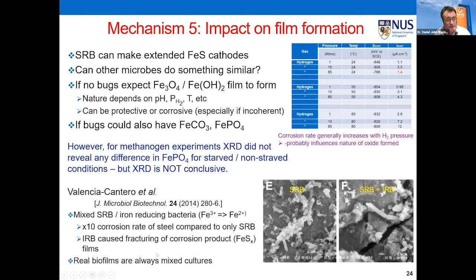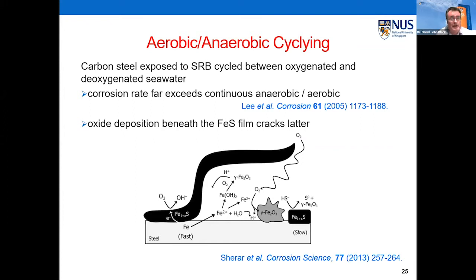And they found that the presence of the iron-reducing bacteria, that's iron 3 to iron 2, actually caused cracks in the sulfur film that was forming on the metal. And if you crack your oxide film, then you're going to get, this was actually a sulfide film, if you crack that, you're going to get higher corrosion rates. And that's also what Brenda Little and Dave Shoesmith found when they looked at aerobic anaerobic cycling, which always gives you much higher corrosion rates than pure anaerobic. What Dave Shoesmith found, and had some evidence for, was that you make a sulfide film and you let oxygen in, and you'll start making iron oxide underneath the sulfide film, and that cracks your sulfide film. And so once you've cracked that, it's no longer protective and you get more rapid corrosion.